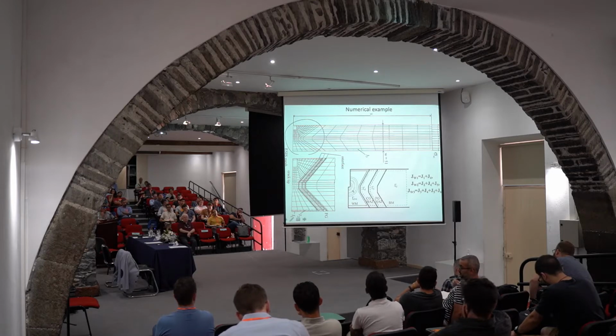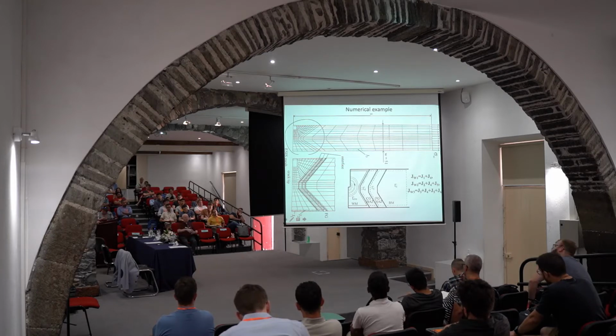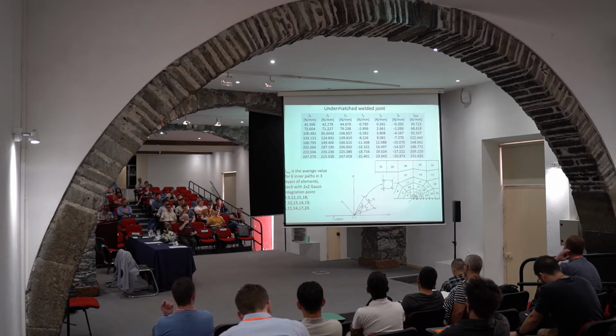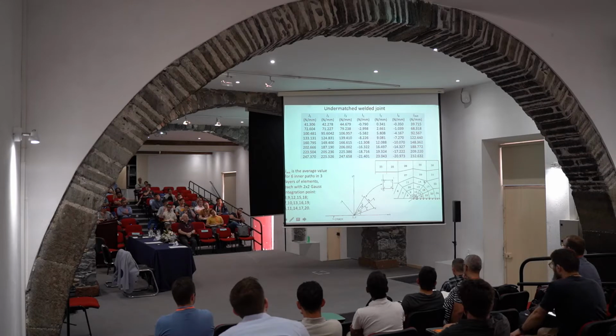Now, to be sure about that error, we need an exact value, which we can get from a segmentation analysis, which is close to exact, of course. And for that, we used 6 paths which are inside the weld metal. They are shown here and they will be shown later as well. You can see here, these 6 paths are in these 3 layers of elements which were positioned at the crack tip. Those were the times where we prepared our input data manually.